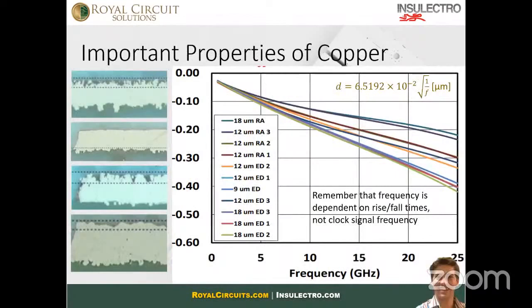But when we start looking at electrical performance properties of ED versus RA, the RA foils really start to stand out. And that's for a number of reasons. On the left-hand side, you can see some examples of ED foil. And then the second one down from the top, you can see is an example of an RA foil. Now, keep in mind, I don't have the ability to see the grain boundary in these pictures, but you can see the smoothness of that foil is significantly less than that of the ED foils. And when you start looking at your insertion loss and how these factors affect your electricals, you can see on the right-hand side, we've profiled a number of RA and ED foils from multiple manufacturers and multiple coatings.